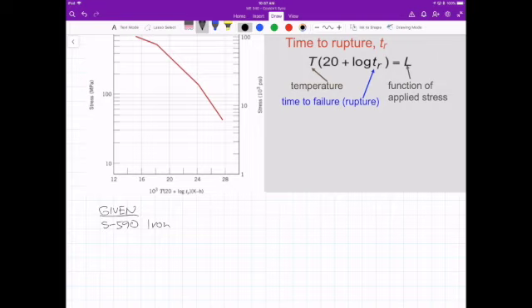We're given an x-axis that is related to temperature, 20 plus the log of the rupture time, time to rupture, and that's in Kelvin hours, so that comes right from here. So that's our dependent variable. We'll plug in the psi on the y-axis, and we can determine the temperature and time from the x-axis.